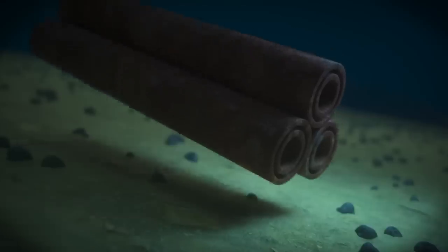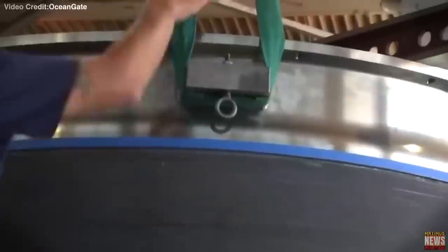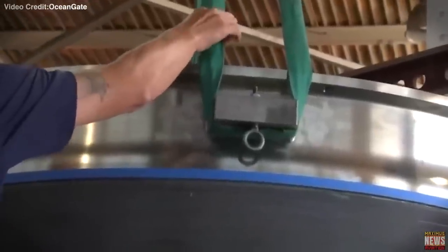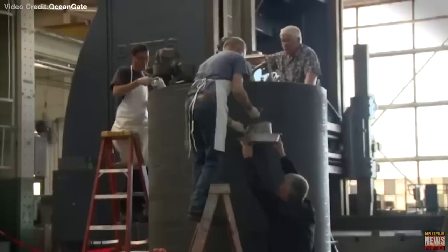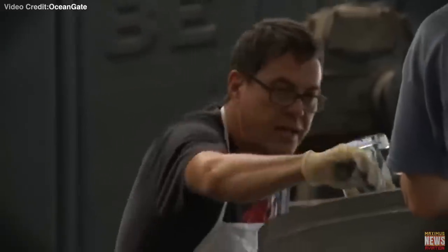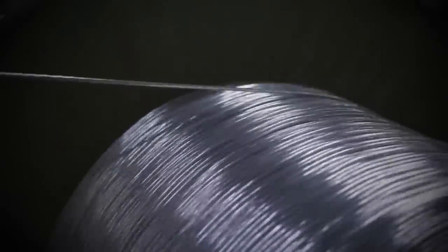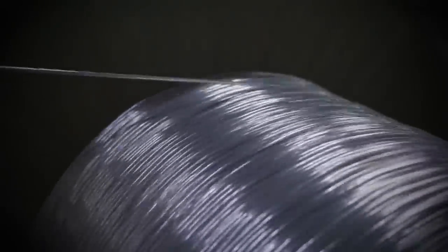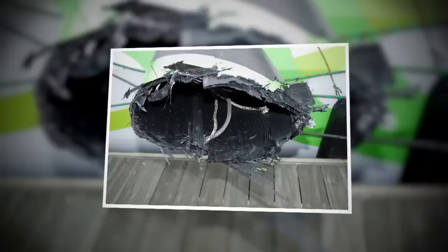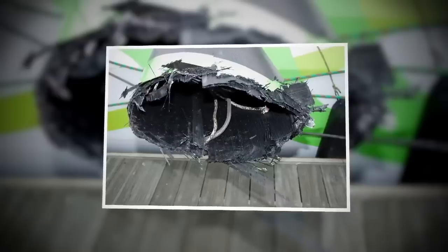This elevated pressure can lead to more wear and tear on the material and potential separation of its layers. The wear and tear can be compared to bending a wire repeatedly until it breaks, while the separation of layers is akin to splitting wood along its grain, which is easier than cutting across it. These factors made the hull more susceptible to failure under the extreme external pressure experienced at the depths of the